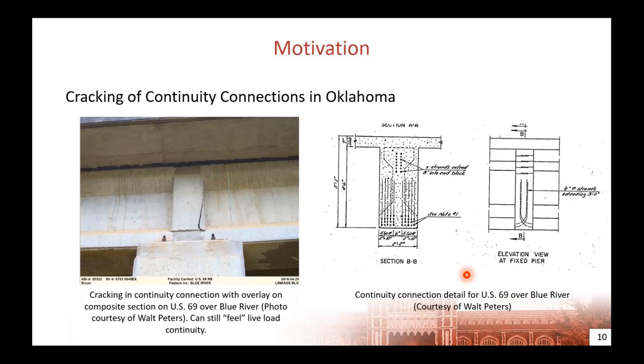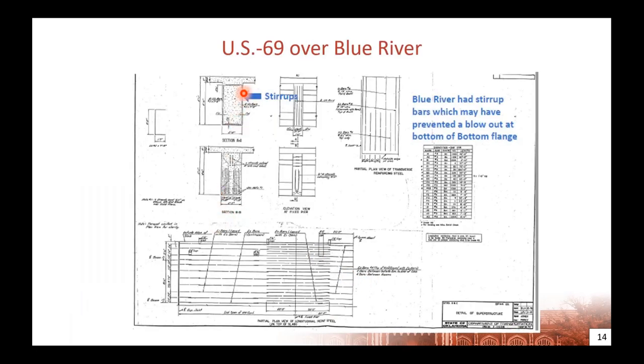Okay, well, a type 4 beam is 26 inches wide. So there's about a foot opening between the two girders. And basically you make a chunk of concrete going from the bottom of the bottom flange up to the deck. And generally, a lot of them, the only reinforcement was the strands. In a few of them, we put a few stirrup bars. And like Wolf Creek had a lot of pre-stressing strands that extended out of the beam besides the ones that were about 3 feet long or 2.5. So that's the best I can describe it.